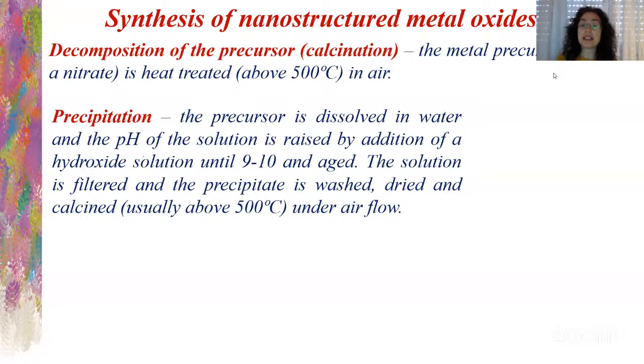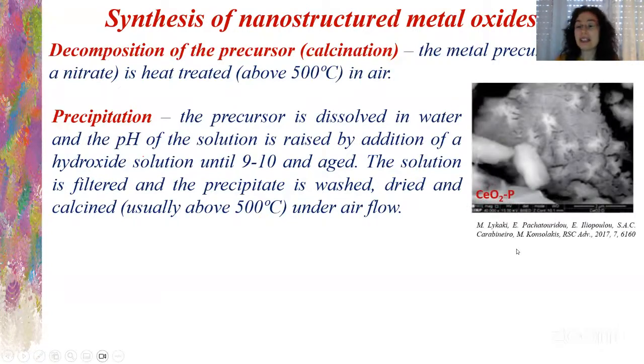So the precipitate is washed, dried in an oven and calcined, usually above 500 degrees in airflow. And we have here a nice SEM image of cerium oxide obtained by precipitation.